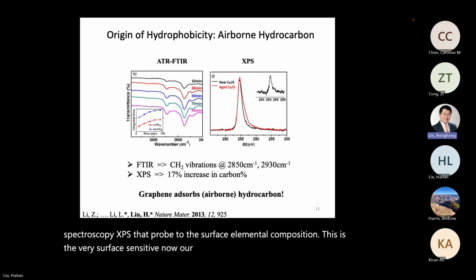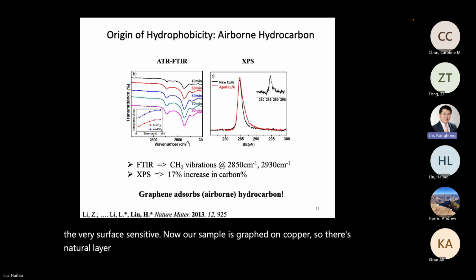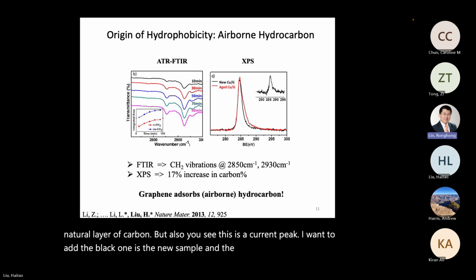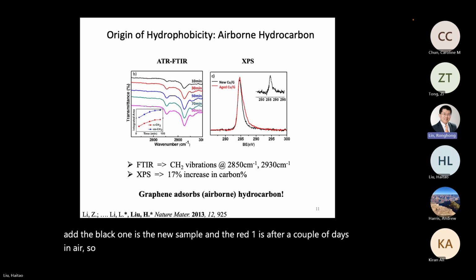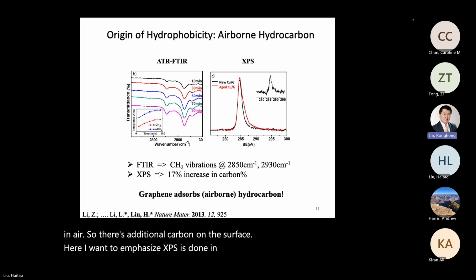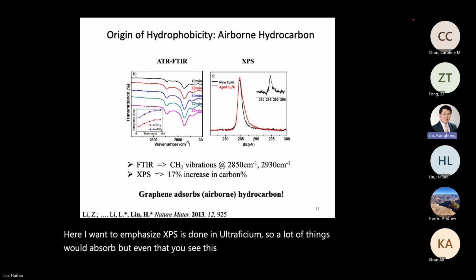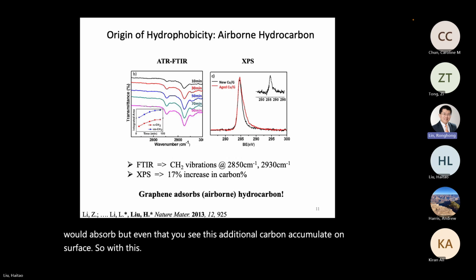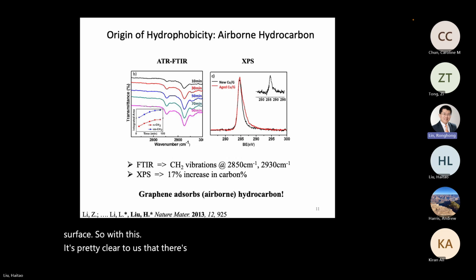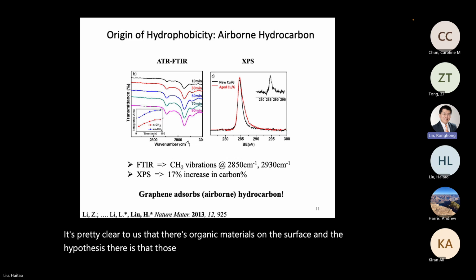This is very surface sensitive. Now, our sample is graphene on copper, so there's naturally a layer of carbon, but also you see this is a carbon peak. The black one is the new sample, and the red one is after a couple of days in air. So there's additional carbon on the surface. Here I want to emphasize XPS is done in ultra-high vacuum. So a lot of things would desorb, but even so, you see this additional carbon accumulating on the surface. So with this, it's pretty clear to us that there's organic material on the surface. And the hypothesis is that this organic coating from air changes the wettability of graphitic carbon.